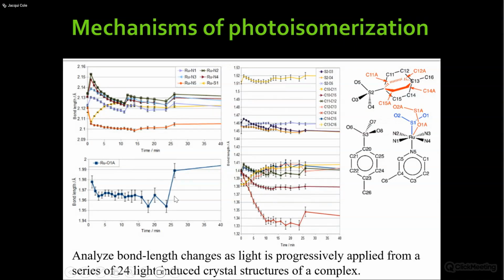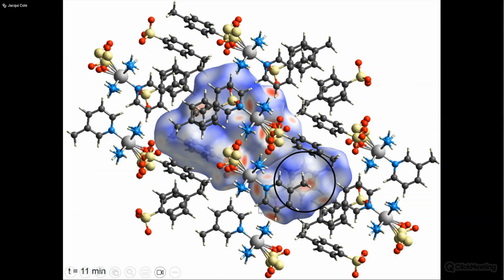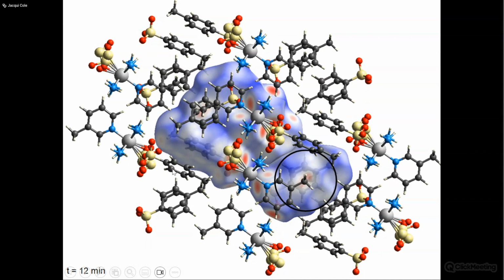So let's have a look at what we see. After a long time, I looked at all sorts of differences, and between 11 and 12 minutes, this is what I found, and it's pretty subtle. I'm showing you Hirshfeld surfaces, and I've circled this area here because it's super subtle. I'm going to flick between 11 minutes and the exact same slide as an overlay of what you see at 12 minutes, and you just have to look at the bit in the circle. Did you see it?